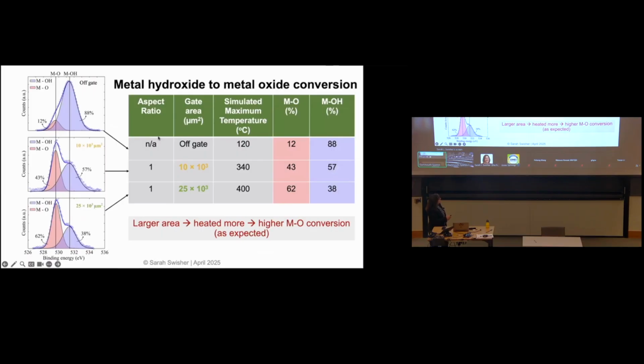The other thing that we used to help validate this model was the interrogation of the bonding environment, or the chemical structure. This is that XPS data again, for those who are familiar with this. The purple getting big is bad. This is where it starts. Off that gate, even though it sees that same photonic curing pulse, it's not getting converted. It's staying in this hydroxide form. Then as we increase the area here, the maximum simulated temperature goes up, and we see an increase in this oxide fraction, which is exactly what we want. So the larger area causes it to be heated more, which means we get more of this metal oxide conversion.